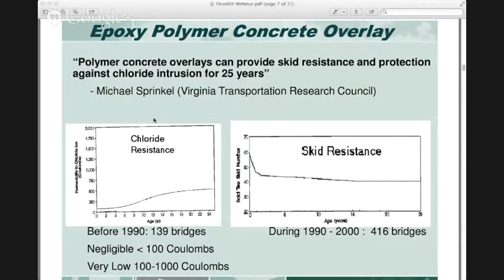And on the left graph, this one just indicates the chloride permeability. It's showing a very low Coulomb rating of about 500 or so after 25 years, which is considered quite low. Anything below 1,000 is considered very low, and below 100 is considered negligible, which is where these products typically start out from years 1 to 4 or 5. Next slide.